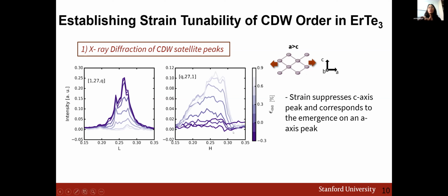As we increase the tension that's applied to our sample, though, we see a suppression of that L axis CDW peak, corresponding with the emergence of a CDW superlattice peak along the H direction. So indeed, it seems to suggest that the CDW wave vector can be reoriented by 90 degrees with the application of uniaxial strain.